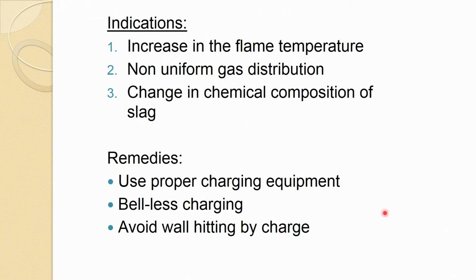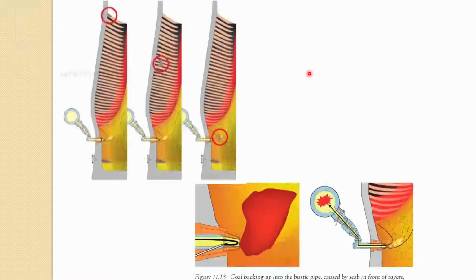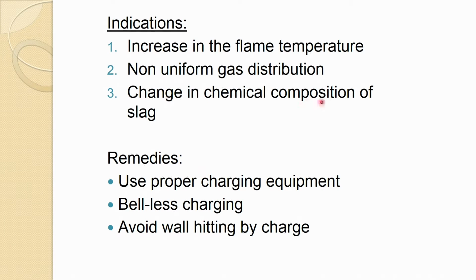So, the indications are increase in the flame temperature, non-uniform gas distribution. Naturally, it is blocking one of the tuyeres, so there would be a non-uniform gas distribution, and a change in chemical composition of the slag. So, the remedy is to use proper charging equipment, bell-less charging, and avoid wall hitting by the charge. Bell-less charging actually gives you this advantage that it does not hit the wall, so there is less chance of creating fines. Mostly it is also about the quality of the charge, which should be strong enough, and the proper charging equipment should be used, starting from the storage bin to dumping it.